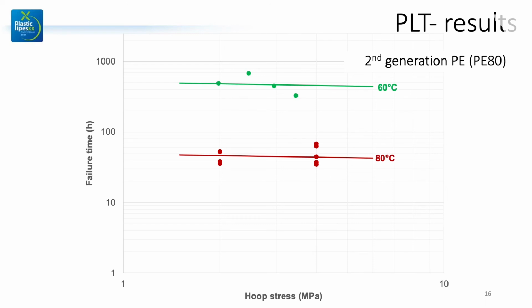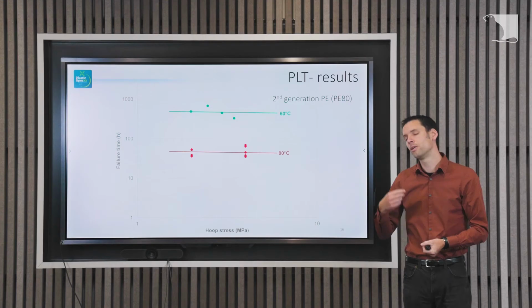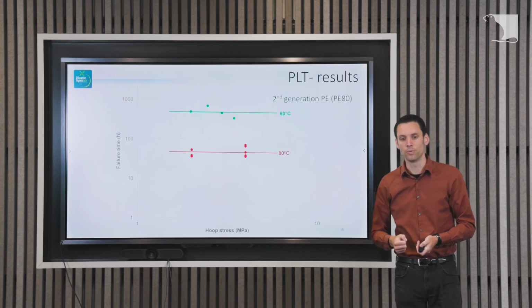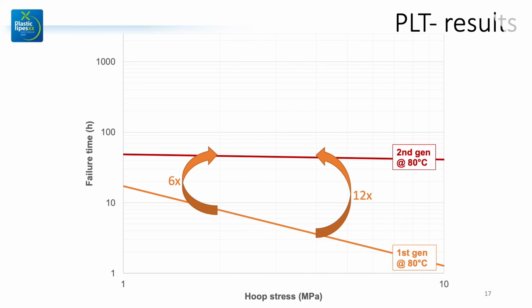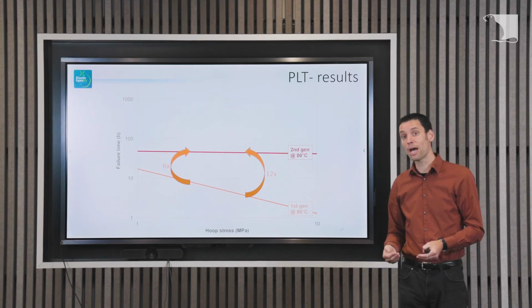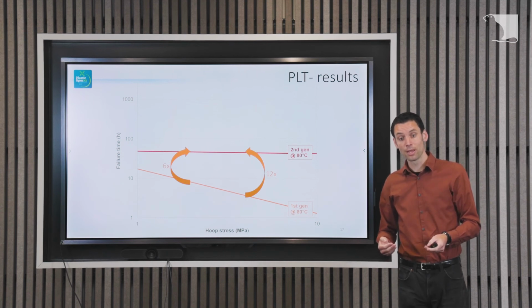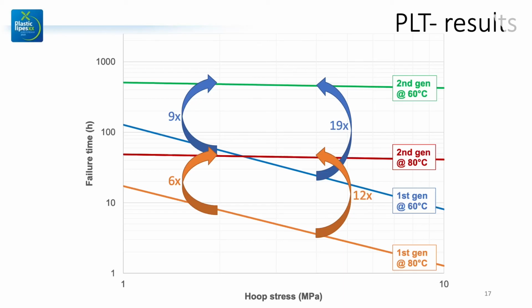So what you see here, again, on the vertical axis, the failure time, and the hoop stress on the horizontal axis, and we don't see any dependency on that hoop stress anymore with the second generation. We also didn't test the 40 degrees because it would take too long to test. And with that, you already see that improvement in material. You see it even better here. In this graph, I just show the 80 degree centigrade lines. And what you see is that the second generation polyethylene is 6 to 12 times as good as the first generation. And if we look at the 60 degrees lines, we see it even increases. So it's even better, 9 to 19 times better, the second generation.